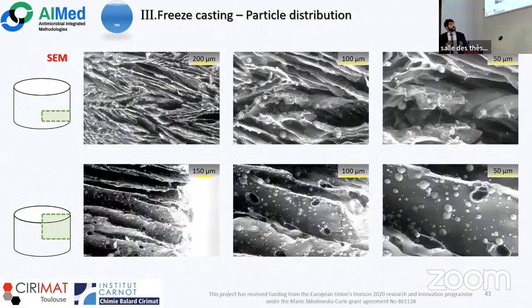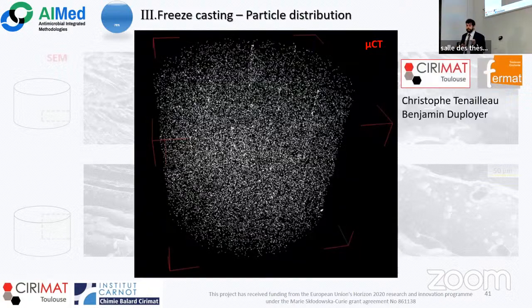Finally, we studied with the SEM the same slice of scaffold to observe where the particles were. And we observed that in all the zones and at all the magnifications, the particles are well and homogeneously distributed. Furthermore, they are embedded in the polymer walls, and their morphology is kept. So the process doesn't bother the structure of the particles. This was also studied with the micro-CT, doing the region of interest preparation, and we observed the corroboration of the good distribution of the particles.